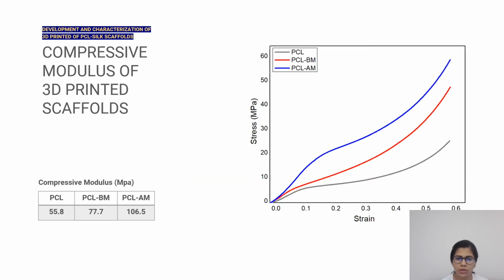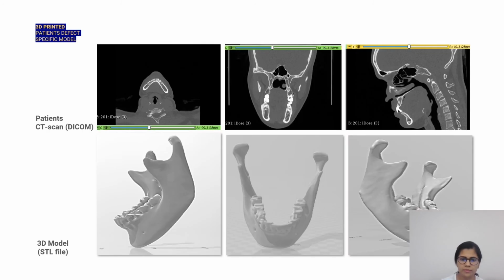Next, we have undertaken compressive testing to understand the strength of these 3D printed scaffolds. PCL with Antheraea mylitta has shown the highest compressive modulus when compared to PCL with Bombyx mori as well as pure PCL scaffolds. So with the addition of silk, we could say that there is an increase in the strength of these scaffolds.